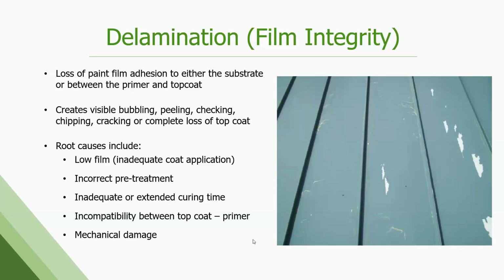But the one we probably see the most, which is a tough one for building owners or homeowners, is mechanical damage. So the panels got damaged during installation or during their life, a scratch, a tear in the paint for some reason. You now have an opening where moisture, ice, debris can get in there. It just kind of starts that picking off process that happens with paint. And once you've opened this paint system up to that, it can go pretty quick.